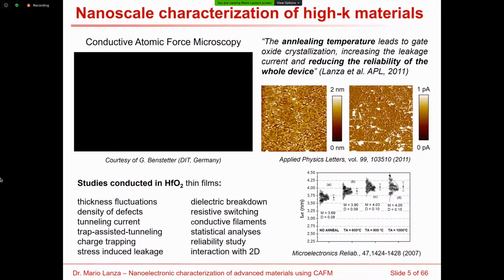One is constructed based on the deflection of the cantilever, the topography, and one is based on the signal recorded by the preamplifier connected to the tip. And that is the current signal. So this is amazing because you can study both mechanical and electrical properties at the same time. In the past, I have used this technique to study resistive switching and dielectric breakdown phenomenon in general.